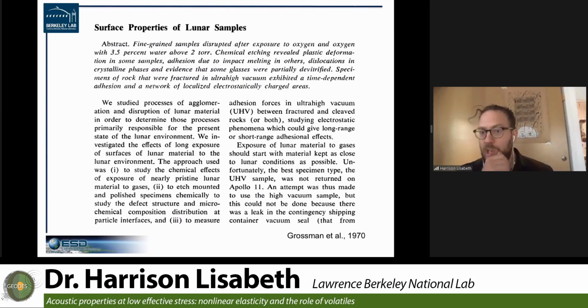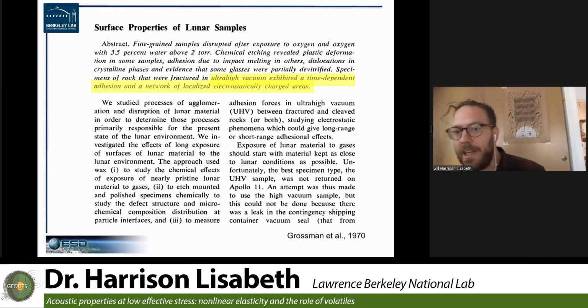And they found some interesting properties, including a time-dependent adhesion and interesting interaction of electrostatic charge. So basically, they put these things under ultra high vacuum, and they noticed that the little crystals stuck to one another and stood up straight. And after some amount of time, they would kind of fall over. And this suggested that the attractive cohesive forces between the grains were augmented in ultra high vacuum.